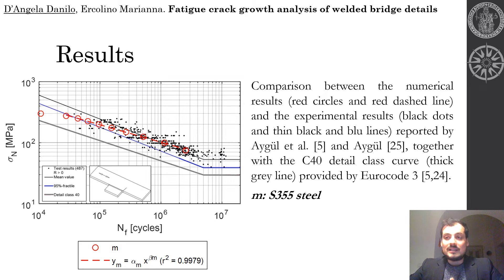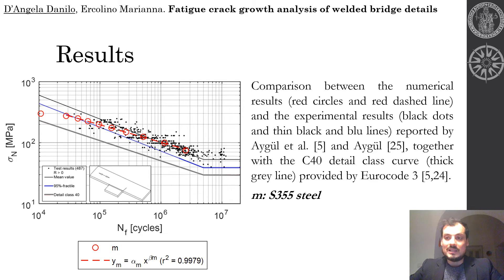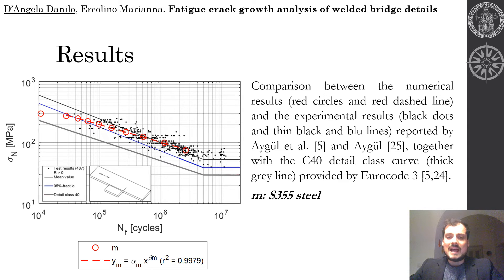In particular, you can see there is a good correspondence between the numerical estimations and the experimental data, even though the experimental data were associated with a much larger range of features of the case study structure. In this case the material was S355 steel.